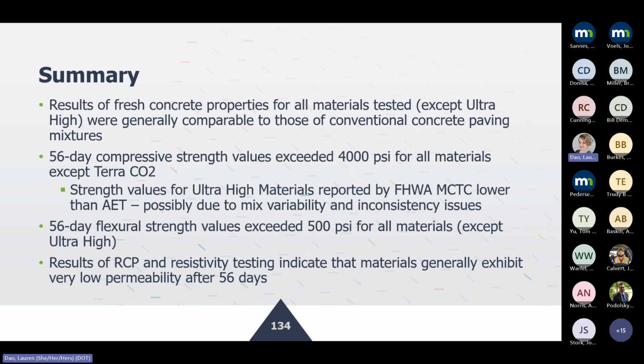So in general, from the laboratory testing that was performed, we saw that the fresh concrete properties were really compatible with conventional mixes, right? And then the compressive strength values, they did do 56-day values also, and they exceeded 4,000 PSI for all the materials except Terra CO2, which was close to 4,000, but slightly less than that. And as you saw for ultra high, there was a lot of variability, probably due to some potential contamination at the batch plant, and also the failure to add the viscosity modifiers and the water reducers in some of the initial mixtures, which resulted in a lot of variability.